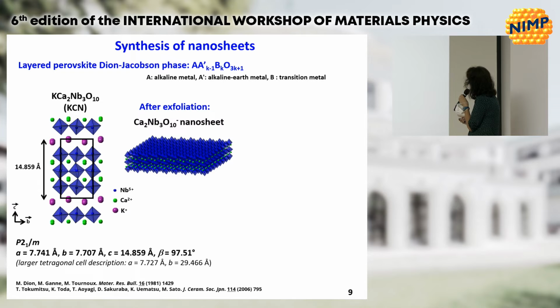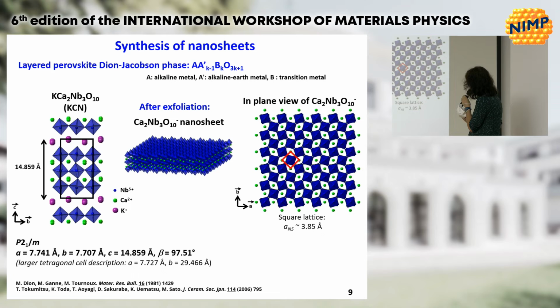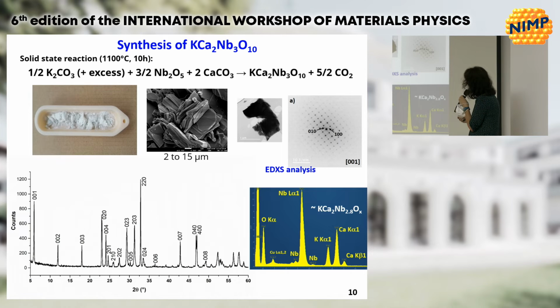So after the exfoliation of these parent compounds, we get the nanosheets. And if we look at them in plane view, we have this perovskite-like structure. So how do we first get the parent compound? We use a conventional solid-state reaction at high temperature. We mixed together the precursors with an excess of potassium carbonate because of the volatility of the potassium.